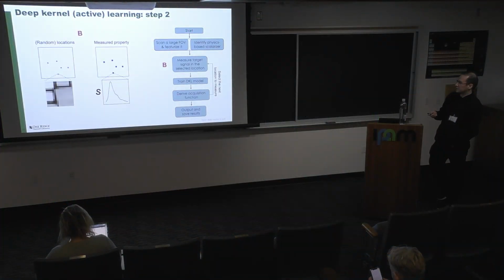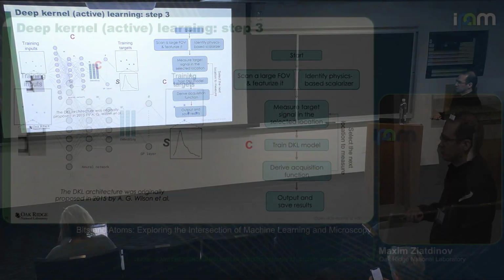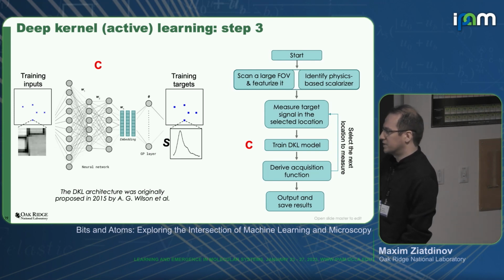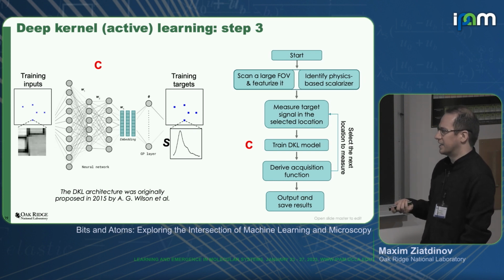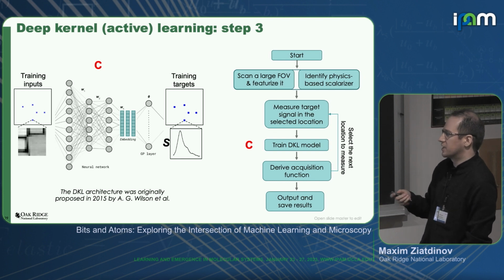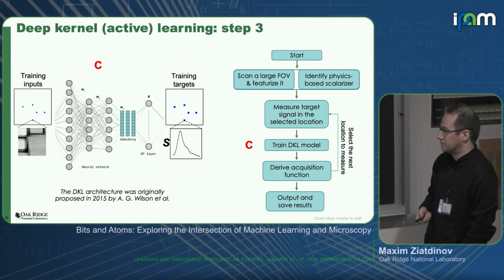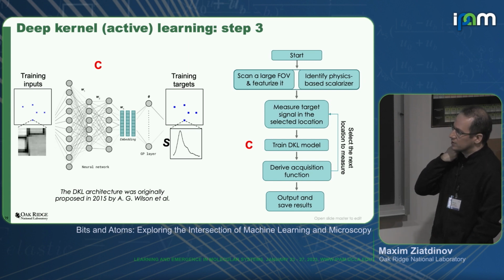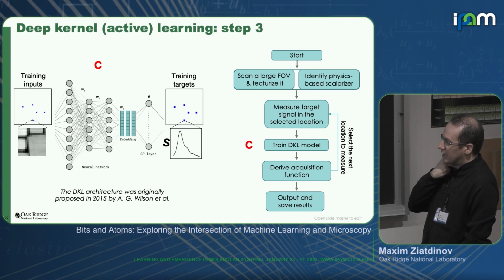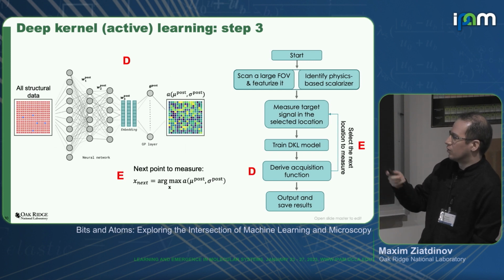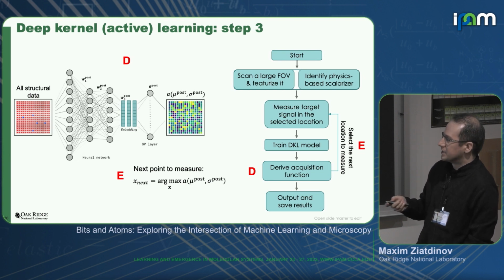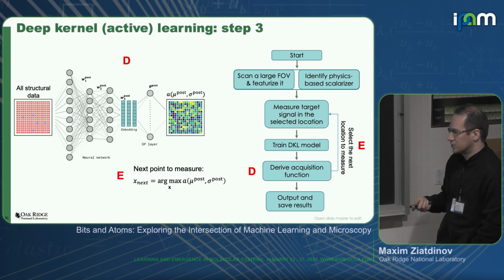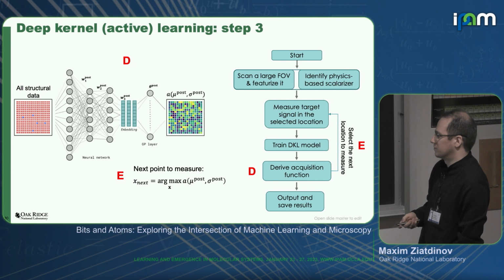Right, so once we did that, we select some random locations and perform measurements there to create some seed data to initialize an active learning algorithm. And then we use deep kernel learning, which was originally, as far as I know, introduced by Andrew Gordon Wilson in 2015. This technique combines a deep neural net and a Gaussian process. The deep neural net takes high-dimensional data and projects it into a latent space where a Gaussian process operates. The weights of the neural net and the hyperparameters of the Gaussian process are learned simultaneously. Once the training is done, you make a prediction on all the remaining patches of data, and you can obtain a predictive mean and uncertainty, which you can combine into the acquisition function to derive the next measurement point. So that's how you do active learning Bayesian optimization, basically.